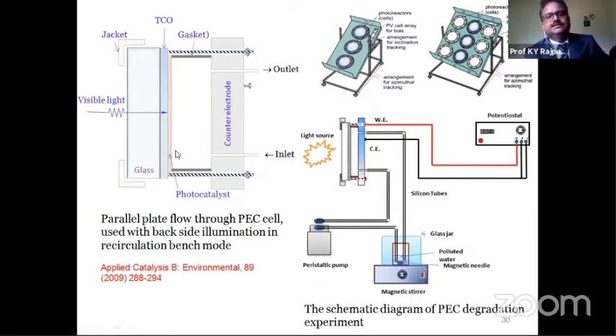And there is a provision for giving the bias between anode and cathode. So this is our cell, and bias is given through a potentiostat, and through the inlet polluted water enters, and through the outlet relatively pure water comes out. So if we continuously circulate this water for maybe 1 hour or 2 hours, then it is possible to completely degrade the organic impurity which is present in the water.